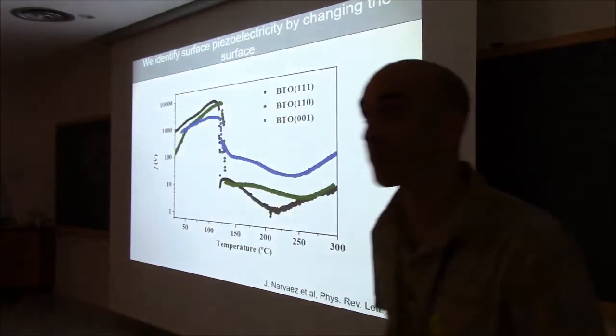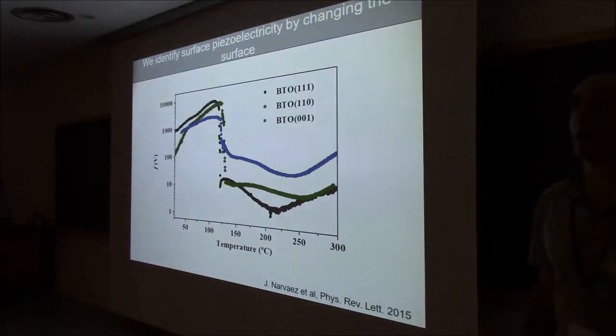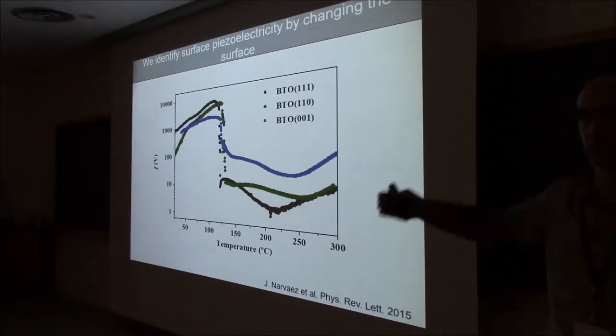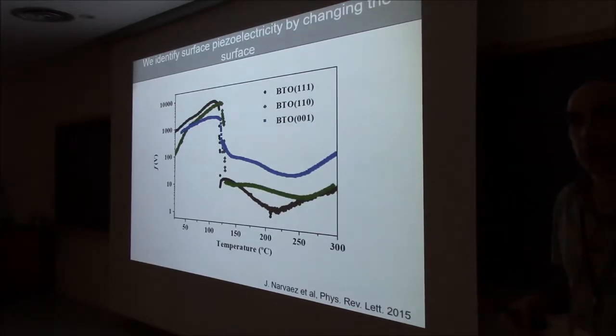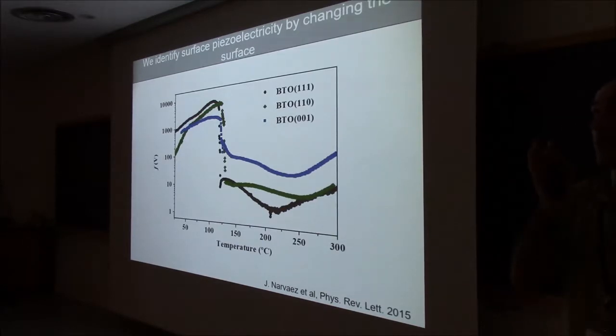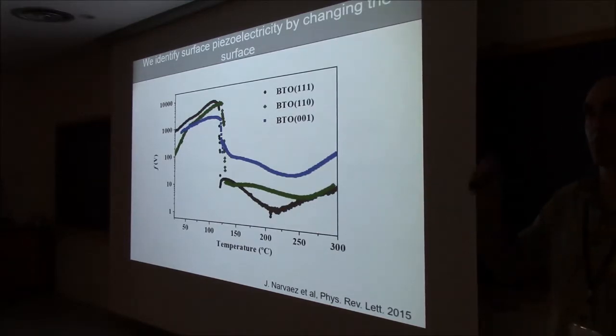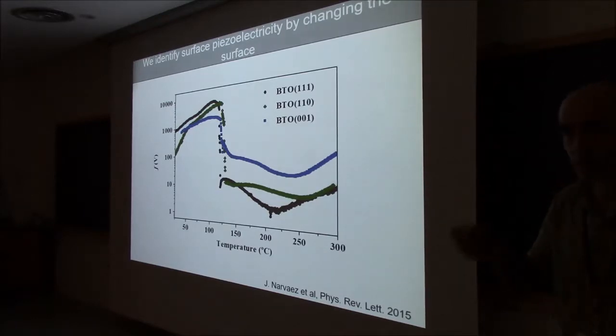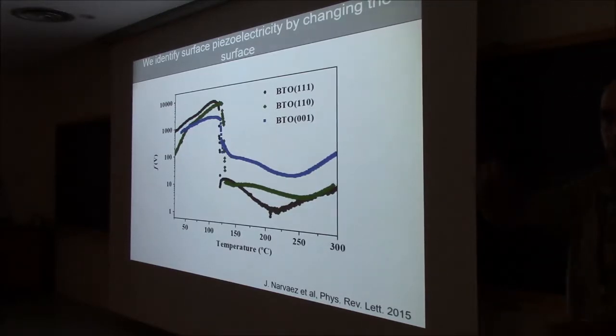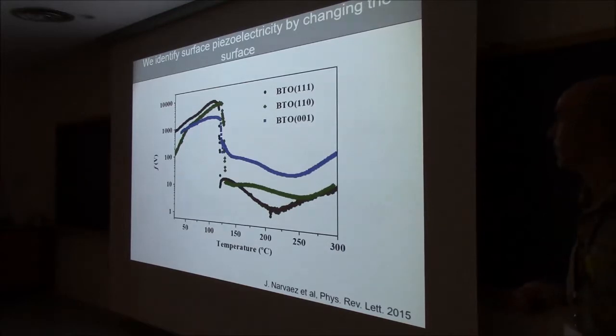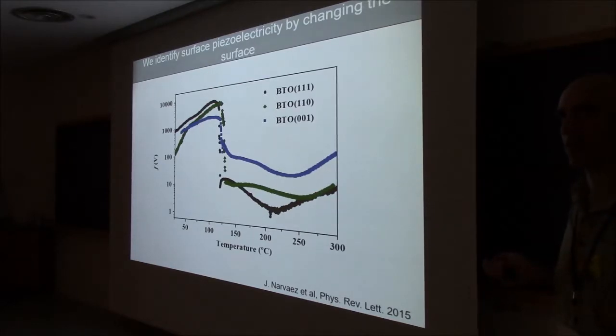What kind of piezo samples did you measure this on? Single crystals. Which size? So they were about 1 millimeter thick, well, one centimeter square by 1 millimeter thickness. We got, well, the 1 millimeter thick ones tend to break easily, so we also bought some thinner ones, but typically between 200 microns and 1 millimeter thickness. It's an expensive experiment because BTO is very expensive, and inevitably we bend them to destruction.